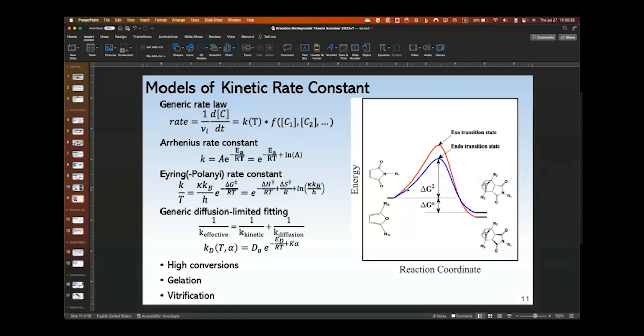Oftentimes these are not called just the Gibbs energy of activation, but the apparent Gibbs energy of activation, so I think that apparent is important. What is kappa in the Eyring equation? Kappa is called the transmission coefficient. It's the probability that a reactant gets over the transition barrier, but in most cases it's just assumed to be 1.